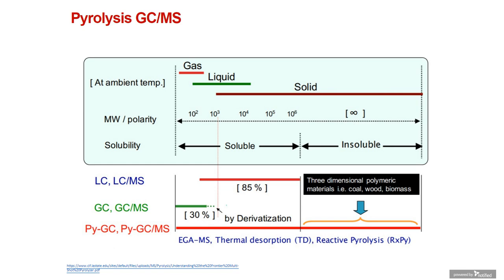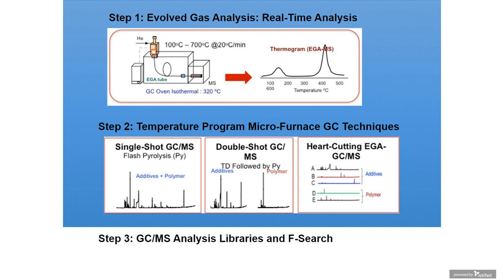The other thing is your inability, for example, to focus on specific regions of the temperature with some of the more common pyrolyzers means that you only have a one-way type of analysis from low to high temperature. Whereas with this Frontier Lab Pyrolysis GCMS, you can jump right away to your temperature region of choice. And as you can see here, the Pyrolysis GC mass spec encompasses, again, all the phases of your sample from gas, liquid to solid.